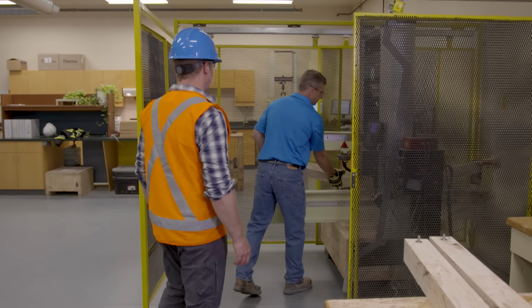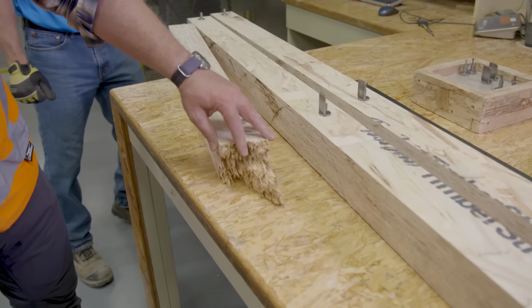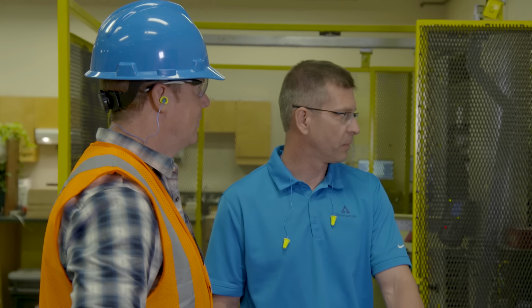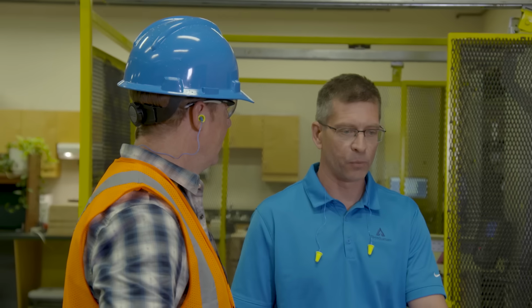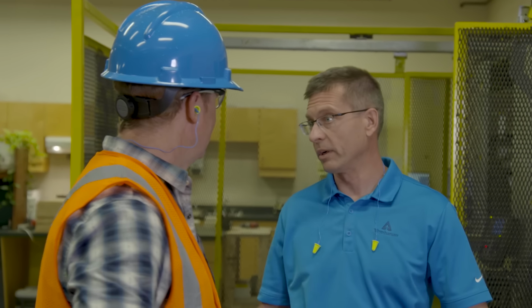All right. That was a full-on explosion. Yeah, that was a good test. So it broke. What'd you learn? What we learned was it took over 4,000 pounds of force to break it, and the data is also telling me that it met its stiffness requirements, or its MOE requirements. So we got a good test. Typically in the lab we'll do 4 more of those samples on the flexure machine, and then over there we're going to actually rip some boards in half on our tension tester. Let's do that. Okay.